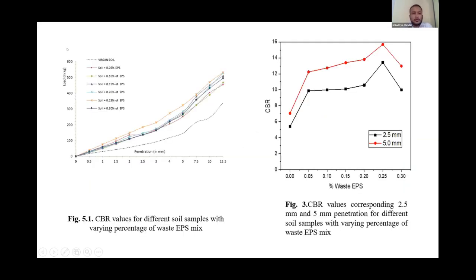And these are the plots for the CBR values for different soil samples with varying percentages of waste EPS mix. If you see the topmost curve, that is the sample which could take the highest load corresponding to the penetrations. We could see that this soil plus 0.25% of EPS was showing us very good results. And if you see this particular graph, this makes it more clear where you can observe a pretty high